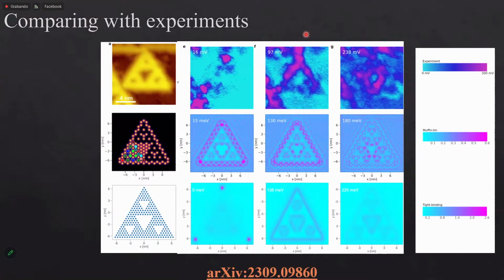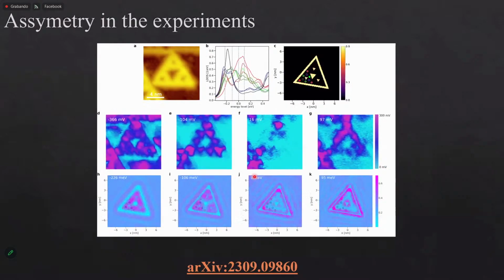And also you could understand some features of the experiments, because if you look at this state, you don't see three corner states as you see here and here. And this we could understand as being related to some kind of asymmetry between the structure in the system and also how the edges look. Also, the edges are sharp, while if you look at our simulation, the edges are a bit wiggly. So for some topological states, this depends on the termination. So we are able to reproduce these features just by rotating the construction, also using sharp edges. So this was something nice.